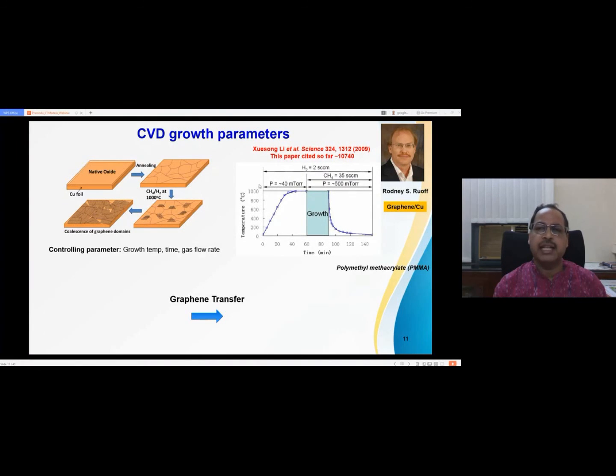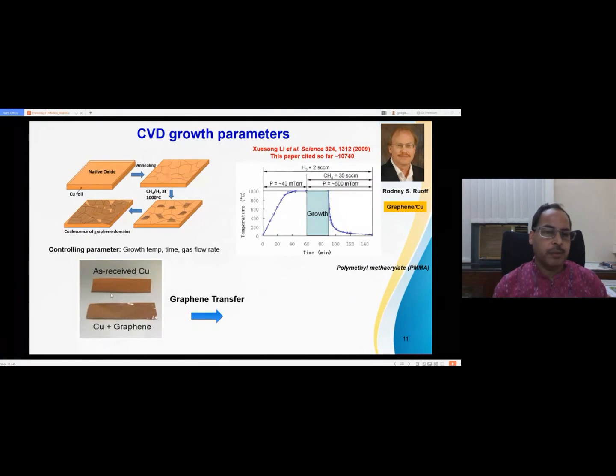At first, he used a high temperature process to prepare graphene film on the copper. So as-received copper looks like this color. When graphene grows on the copper in the CVD chamber, the color changes. And another thing is, in order to do the characterization of the graphene and for other applications, you have to transfer it onto some substrate. So we need a transfer technique.